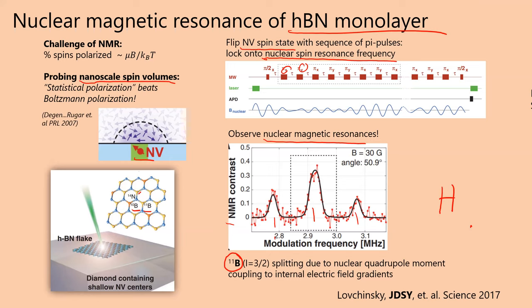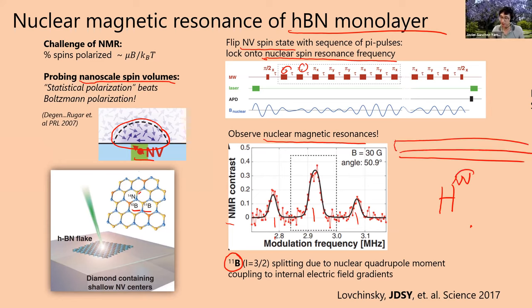Okay, and correct me if I'm wrong, but are you saying that you measure the nuclear magnetic resonance of the single boron atom? Good question. No, look at this picture here. You're always sensing some volume of spins, and actually it's very hard for the NV center to measure the signal from a single nucleus. It's too small of a signal. So in the end, we're probing at least thousands to 10,000 spins at a time, and we're integrating that signal. Is that because of the sensitivity or the spatial resolution? Spatial resolution. The NV center is sitting some distance away from the material, and because of that, it naturally probes some area roughly given by the distance of the NV center to the material. Okay, thanks. Yeah, no problem.